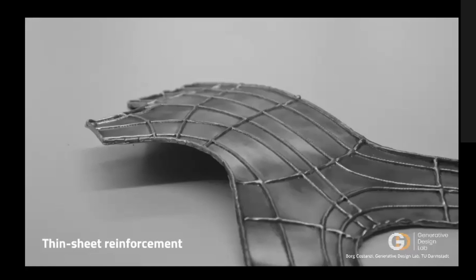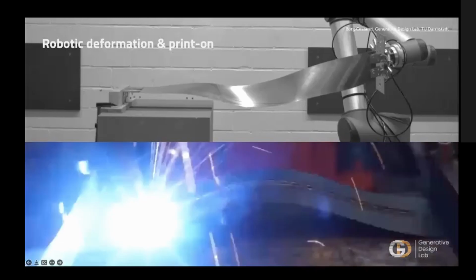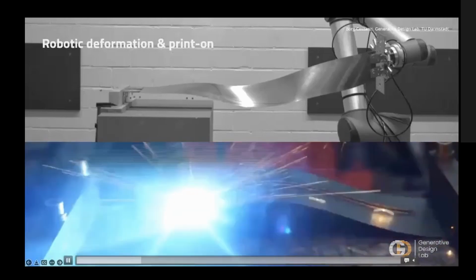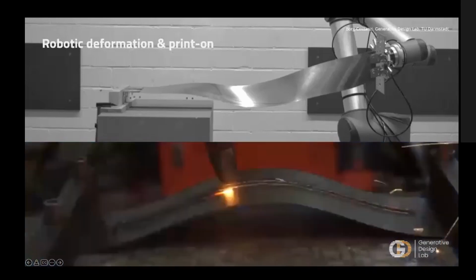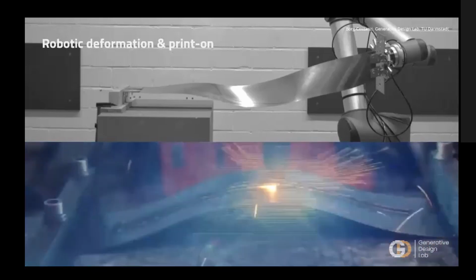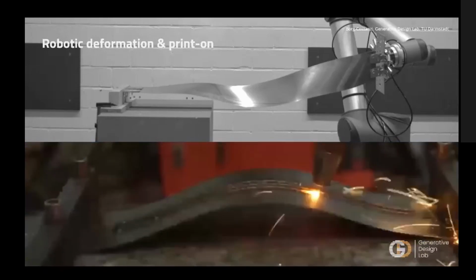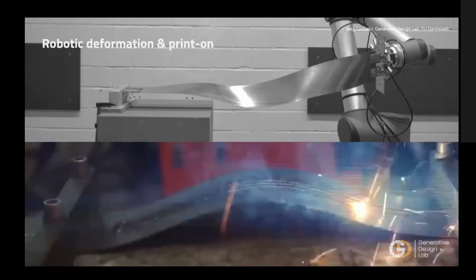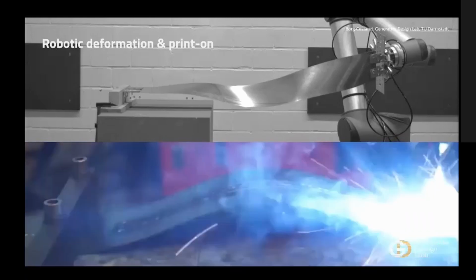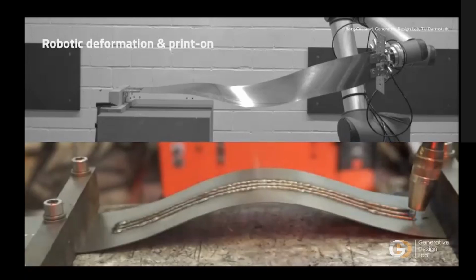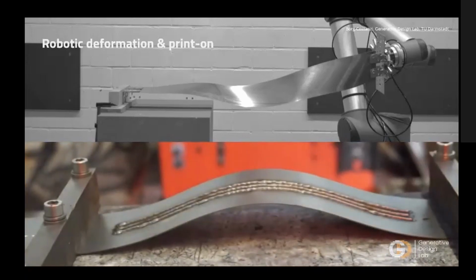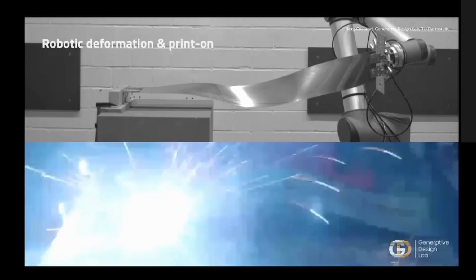Wire additive manufacturing can also be used for the reinforcement of existing steel structures by just welding on top of them. And in our case, we examined the particular case for the reinforcement of very thin sheets. So here we elastically deform sheets as shown on top, and then print on the deformed shape. We print stiffeners on top of the deformed shapes to freeze the deformed shape and produce relatively stiff, very lightweight, and free form, if you will, facade panels, for instance, because we can generate any kind of geometry that we like with the elastic deformation process.